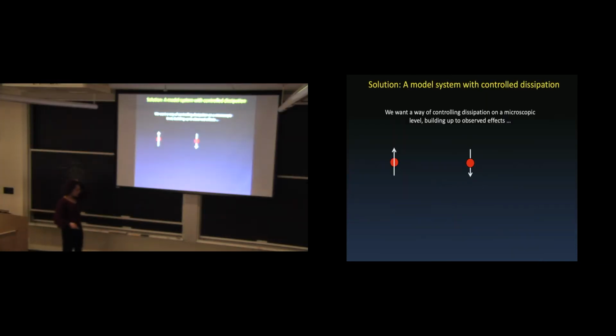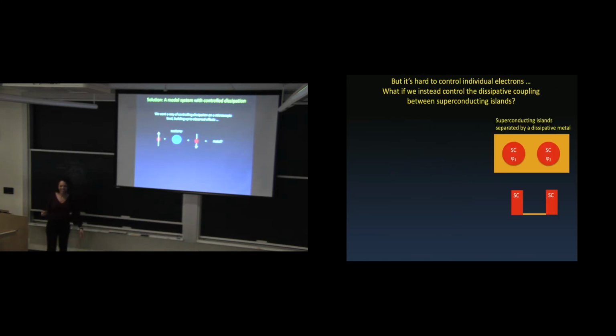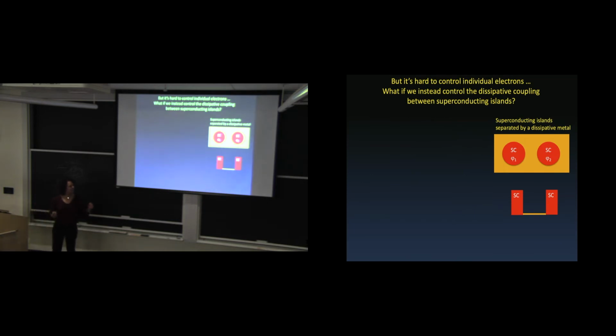Okay, so we use superconductors as our model system, and to understand this influence of dissipation, we really want to add dissipation in a controlled way to a superconductor, and then see if it leads to a metallic state. So we want to take two superconducting pairs and put in something like a scatterer and see if that leads to a metal. Now, of course, we can't separate pairs. That's really hard to do, and if you did that, you'd kill superconductivity. So we did the next best thing, which was we took superconducting islands and separated those with a metal where we could control the amount of metal between the islands, and then we wanted to see how that influenced the superconducting state.